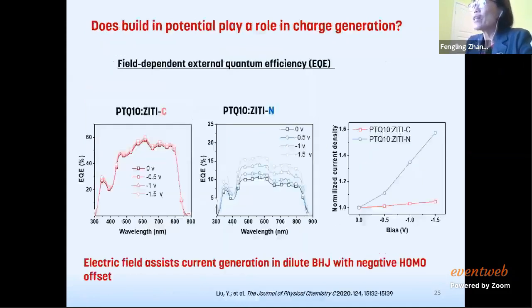Then we check if the field will help to overcome the limitation of this driving force. So we check the external quantum efficiency with the bias on the device. Let me show the different behavior for the two systems. For this ZITI-C, because the driving force is positive, the field does not do much for the EQE. You see, it's a very small increase. But for this ZITI-N system, the field significantly enhances the EQE.